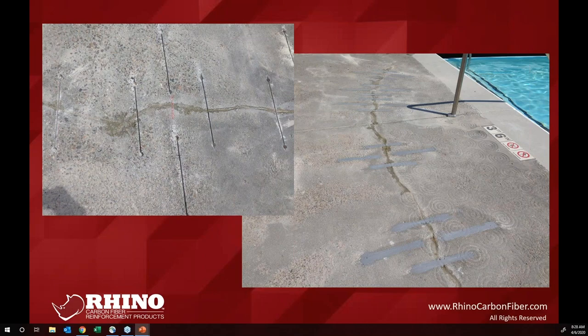Now remember, the biggest thing you can do, and the one thing that people cause the largest problems with, is you can't use compressed air on concrete once you grind on it or cut on it or drill on it. When you use compressed air, the compressed air takes the pulverized concrete and blows it back into the pores. It blows those fines back in, blocks off the pores. So when you go to put epoxy down or anything else down, walls, floor, slabs, columns, whatever, the concrete fines are blocking it. So what you're bonding to is the concrete dust, not the concrete itself. So vacuum is the key. Yeah, you have to use a vacuum.